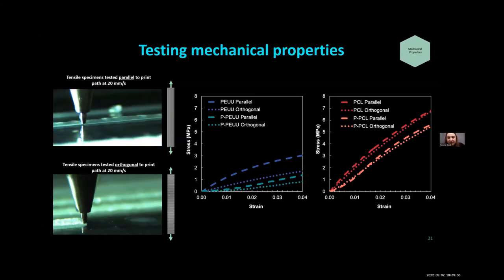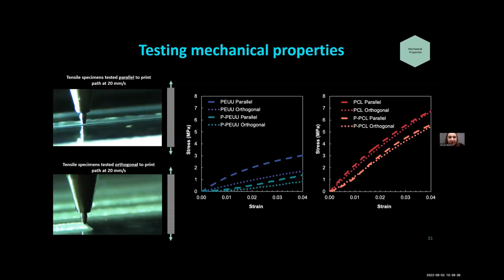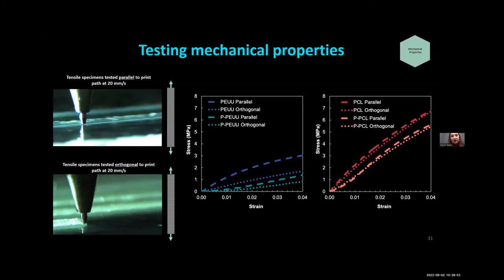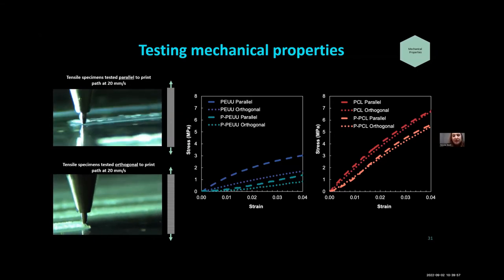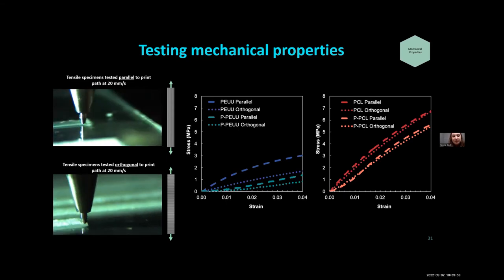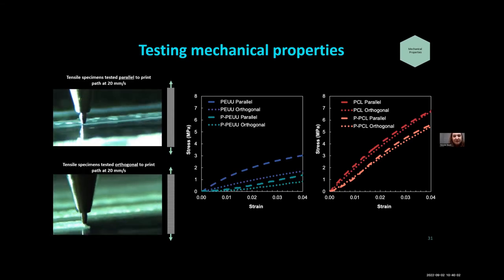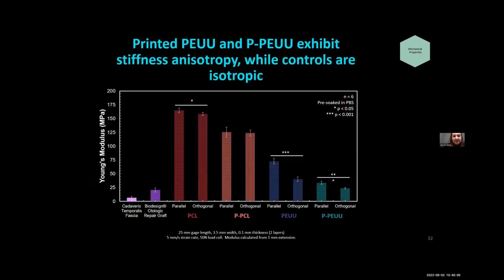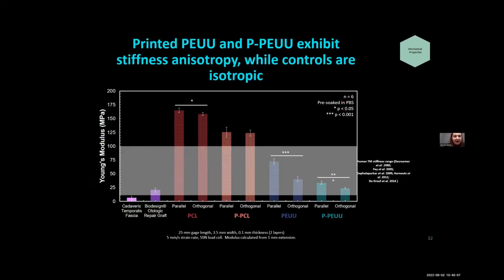And so what we were essentially able to see is that in these polyurethane materials, both with and without this water-soluble component, we were able to achieve mechanical anisotropy, and that these grafts were actually stiffer along the print path rather than orthogonal to the print path. So unlike with PCL grafts that we saw where they were pretty much mechanically isotropic, these polyurethanes actually had this stiffer behavior. And ultimately, we wanted to compare these stiffness values to that of the eardrum. So as I mentioned at the beginning, we're aiming for about a 10 to 100 megapascal stiffness.